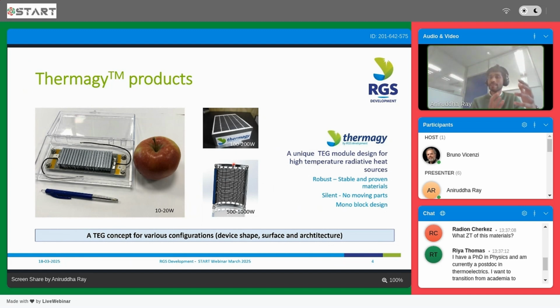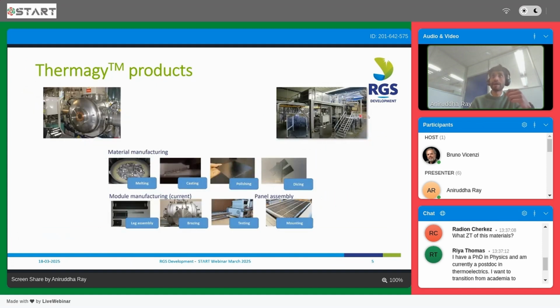These devices we have started producing in our plants, where we patented a way of making silicon germanium based materials. We have built up vacuum induction furnaces from scratch, where we melt the material, cast it, and do all the downstream process of polishing, dicing, as well as assembling the final devices in a brazing oven. We also upscale the production process, imagining an entire 24/7 running process where we can make these wafers in batches as and when needed.